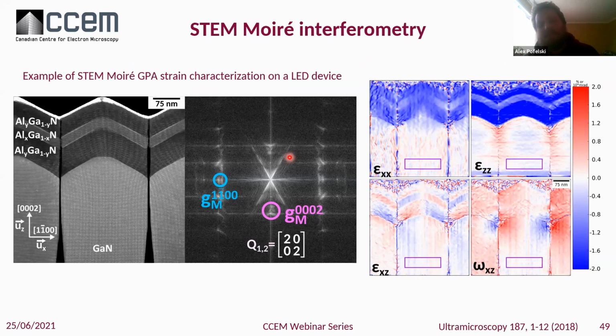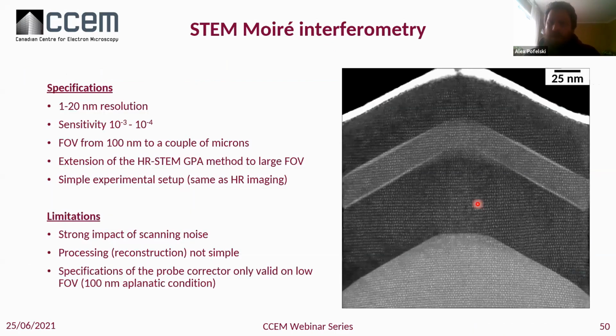Just to show you that this is working on whatever type of device. So this is here an LED device composed of aluminum gallium nitride heterostructures on the gallium nitride substrate. And without going too much into detail, you can have a similar strain maps. So, to conclude on that method.